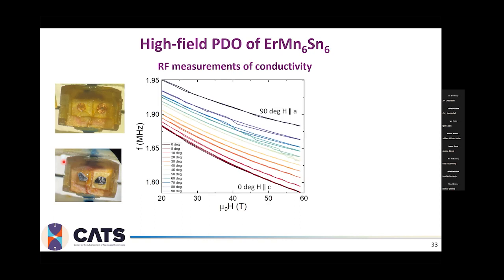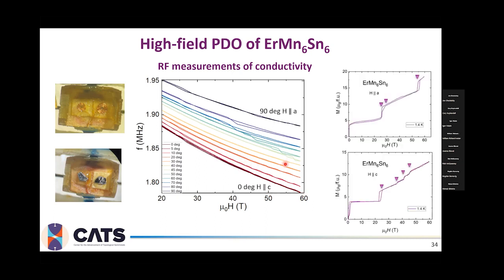So this is the high field part of the PDO response, which I got. With the magnetic field applied along the C direction, we indeed can see some quantum oscillation. However, when we move towards the A direction, we can see that around 40 degrees, the response of the PDO is dominated by the magnetic phases in that material.